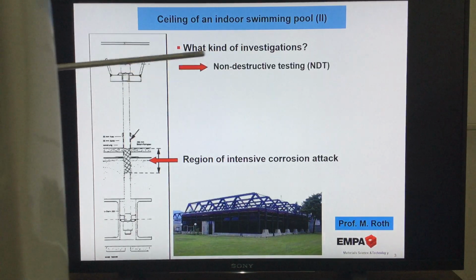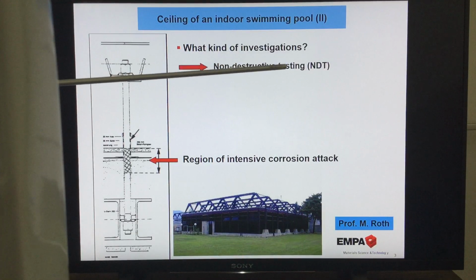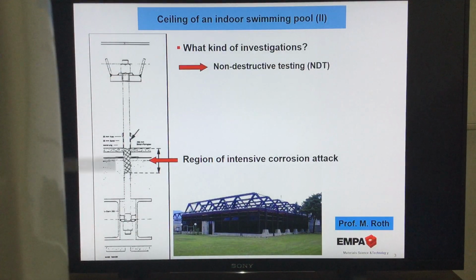It's so-called non-destructive testing. So we have the whole bar, the whole screw, which we see here, the steel hanger. There are different ways of non-destructive testing. One way is, for instance, you apply a certain color on the material, and you go under UV light, and in UV light you will see if there are indications of cracks, and there you can investigate very carefully.